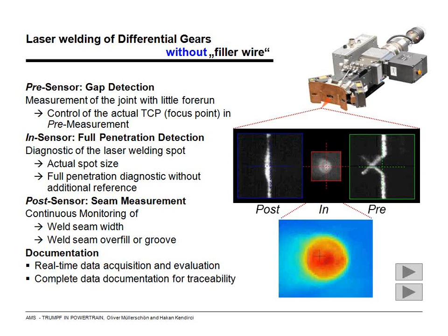With this sensor, we can have a look directly onto the keyhole, the process itself. We can see absolutely the center of the focused beam and the welding process. With this sensor, it's also possible, if the part is designed in the right way, to get information if we have full penetration reached or not. And in the third way, we also can have information about the quality of the surface of the welding with our post sensor. That means we can get information about if there's an overfill or a groove or an undercut, for example. So we can provide some information about the quality of this process. With this system, we can document a lot of data for the traceability, because we will store many pictures made with our camera system.